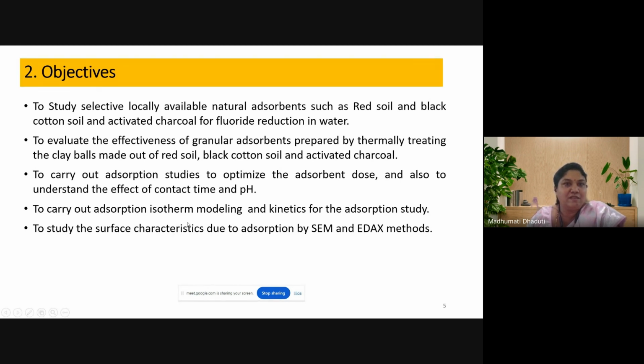The adsorption studies were also carried out to optimize the adsorbent dose and to understand the effect of contact time and the effect of pH. The adsorption study was modeled using isotherm models, and a kinetic study was also done. The surface characteristics of the adsorbents were also studied using SEM and EDAX methods.